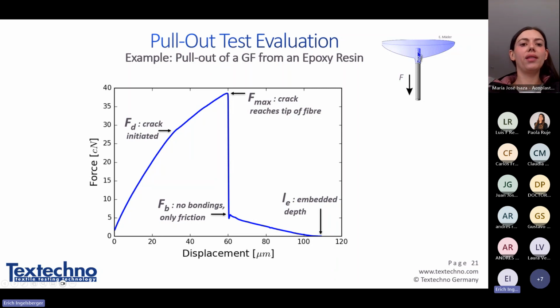And because of this meniscus, usually there is some additional length. This complete wetting length, or embedding length, is measured when the force drops down to zero. Here the fiber is completely pulled out of the matrix. So then you know the length which is embedded into the matrix.